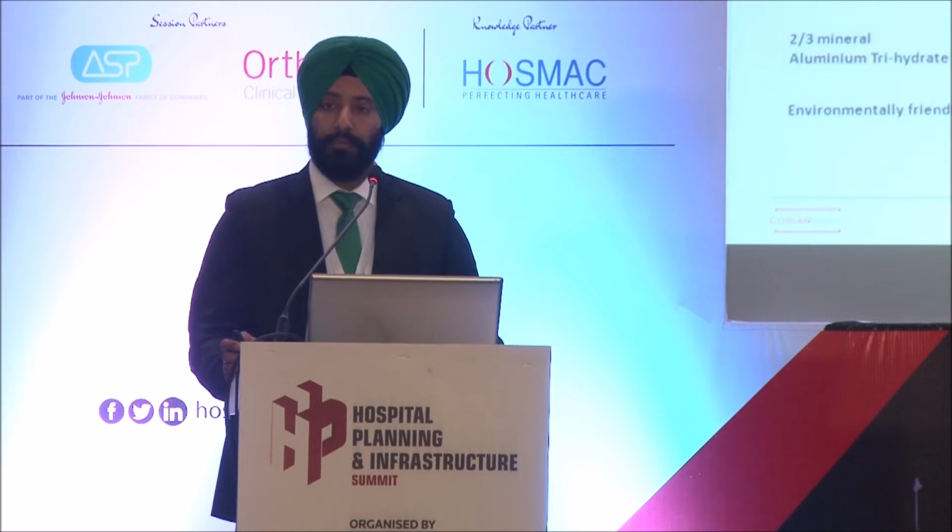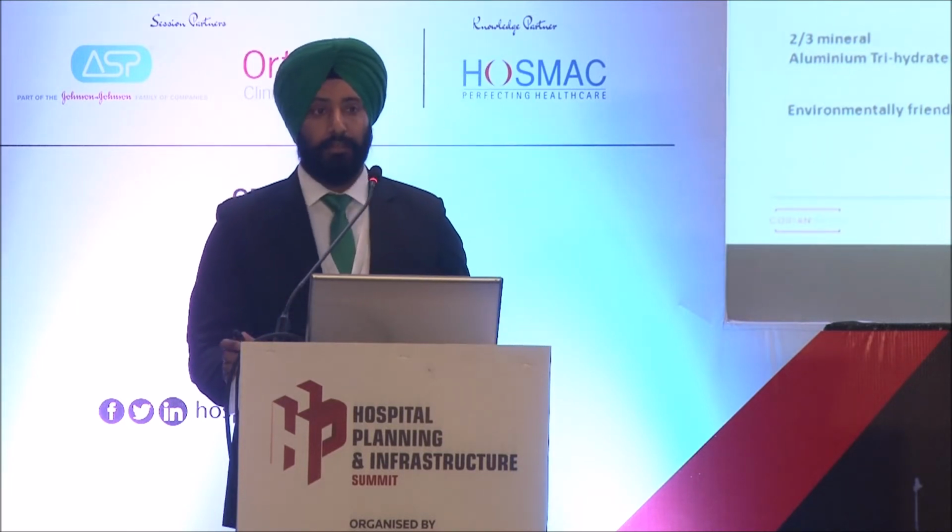So Corian has been in this space for almost 50 years. In 2017, we celebrated 50 years of Corian. This was a home invention done by DuPont scientist Dr. Slocum in 1967. So what does this material consist of? It is one-third PMMA, which is polymethyl methacrylate, and two-thirds mineral, which is derived from the bauxite ore, which is ATH, aluminum trihydrate, and then some environmentally friendly pigments.